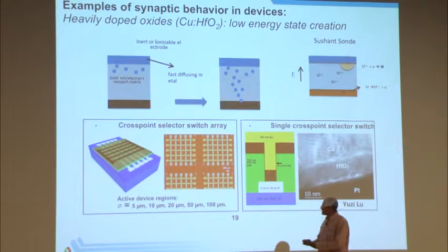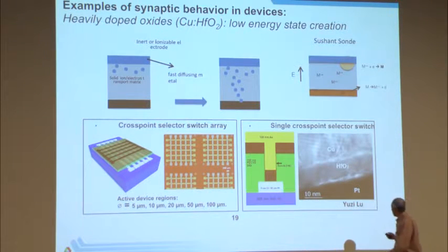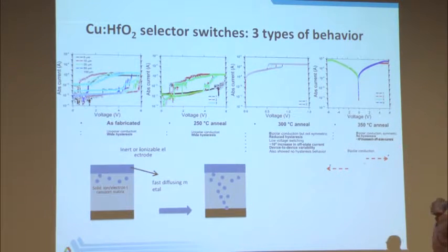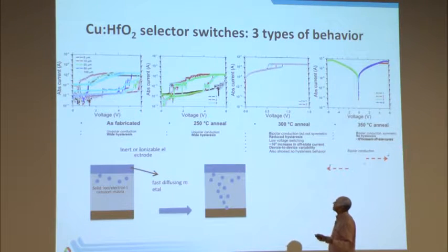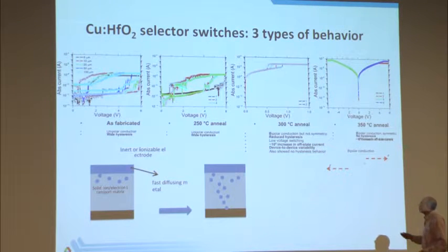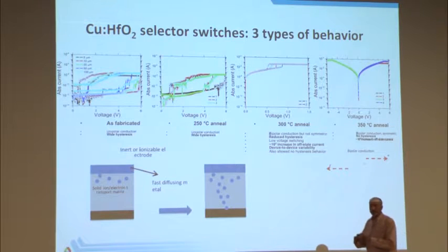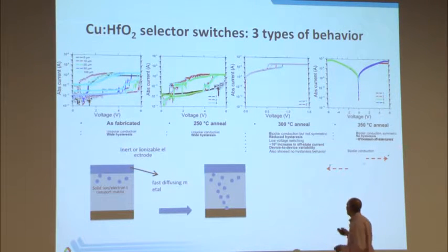Okay. Shown here is a TEM image of this type of device, copper, hafnium oxide, platinum, and thanks to Yuzi for doing the TEM of this work. Now we've been looking at these devices and they show a rich, very interesting set of behaviors. Okay. So if you look at, as fabricated, these devices work at a very high voltage. They show the hysteresis that you expect. There's a lot of variation from device to device simply because the individual devices are rather big over here.